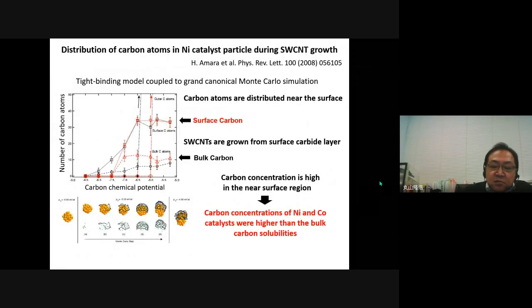Also, I'd like to mention the theoretical simulation about metal nanoparticles during single-wall carbon nanotube growth. Amara calculated the distribution of carbon atoms in a nickel catalyst particle during single-wall carbon nanotube growth. They demonstrated that carbon atoms were mainly distributed near the catalyst surface, and single-wall carbon nanotubes were grown from the surface carbide layer. This means that carbon concentration is high in the near-surface region. We consider such a situation might occur for nickel catalyst. As a result, carbon concentration of nickel and cobalt catalysts were higher than those of bulk states. Next, please.